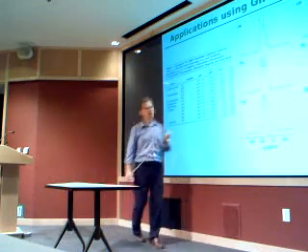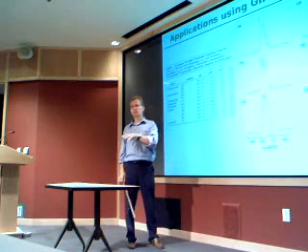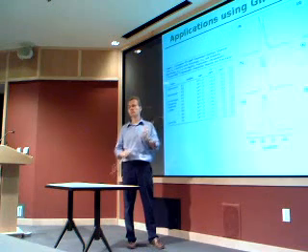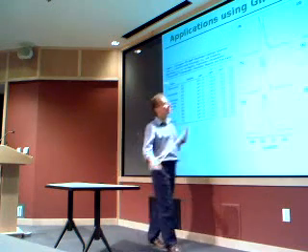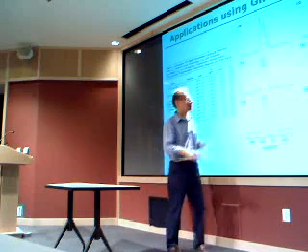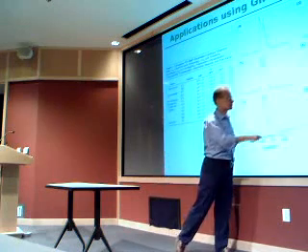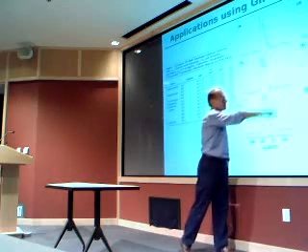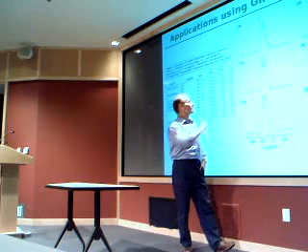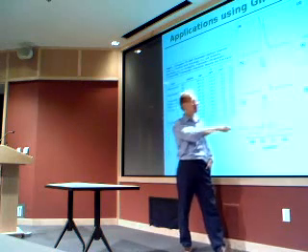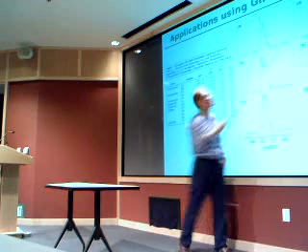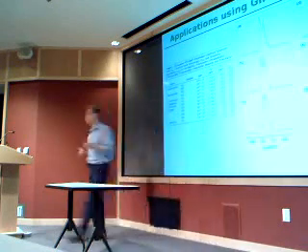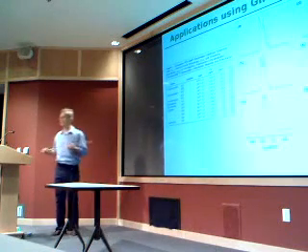So this is again the same table. One can simulate how that would transform into the experimental spectrum. In solids, you don't get such simple peaks, like I showed you before, with the finite correlation times, but you get something which looks a bit more strange. So you get a line which is not that smooth. That's the experiment. Using these parameters, one can simulate the spectra, and you get, I would say, very encouraging agreement. So also for this material, you get that.